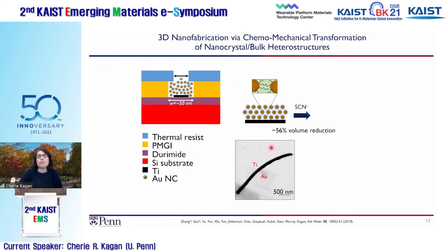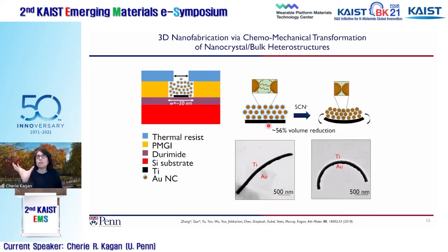As I introduced at the very start, we can change the surface chemistry. If we immerse this structure in thiocyanate, as I showed you before, all the particles want to come closer together. They want to compress both laterally and vertically. As these structures pull together on the top surface, if we free the bottom from the surface, then the whole structure wants to bend. We create a large compression here that creates misfit strain at the interface between the nanoparticles and the metal, and the structures start to fold in three dimensions. You can see that here: the titanium is on the outside and the gold is on the inside.